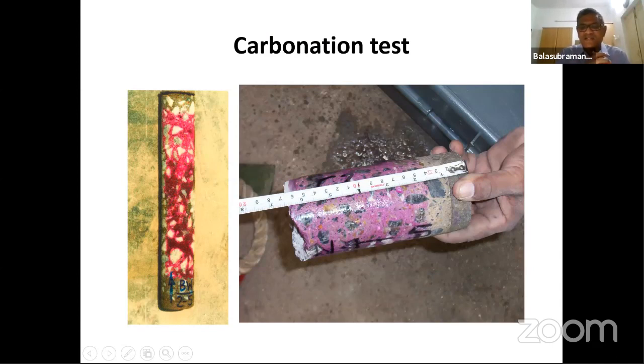Basically, why we do this test is that during repair and rehabilitation, we always want to chip off the bad concrete. So if the carbonation depth is 25 or 30 mm, then we chip off that carbonated concrete and then give fresh concrete. Put a micro concrete or a polymer modified mortar, as the case may be, depending on the thickness. So this is the carbonation test.